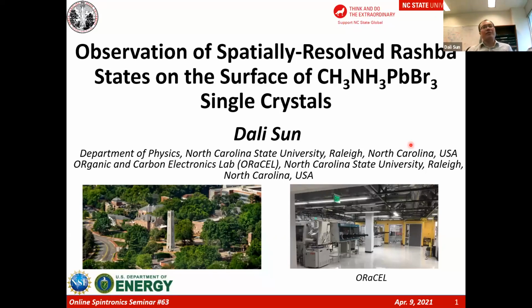The PCE efficiency for this perovskite material was up to 25% back in 2019 already, even comparable with silicon. But instead, what we care about is the spin-dependent features in these hybrid perovskite materials, like the spin Hall effect, spin-orbit coupling, and particularly the Rashba state in such low-temperature solution-processed semiconductor materials. My previous experience was in organic spintronics, molecular spintronics. So it's very natural for us to continue our spintronic studies in these hybrid semiconductors, in contrast to our previous work in organic semiconductors.